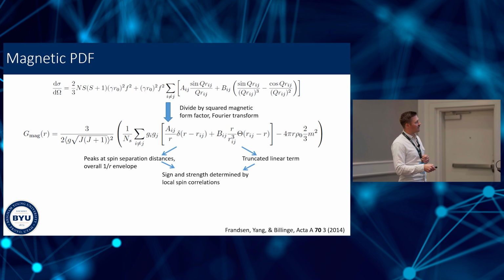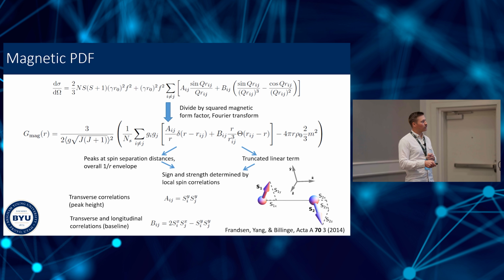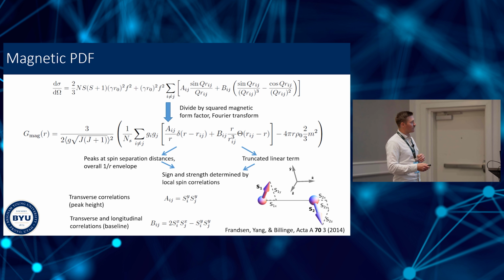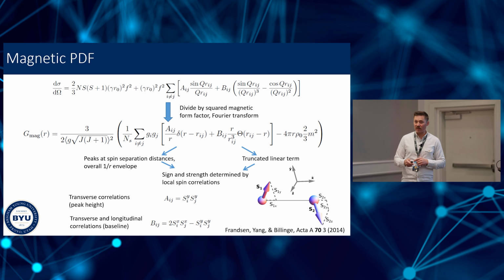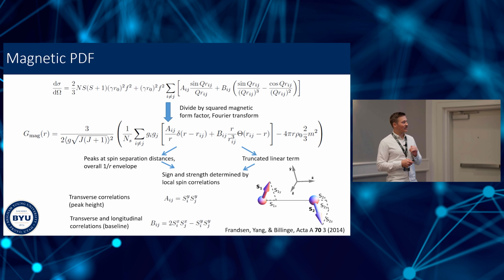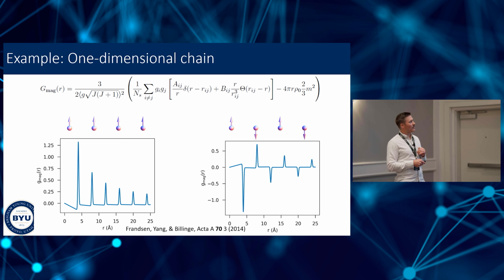The A coefficients give information about the transverse correlations between a pair of spins, transverse to the direction joining those two spins, and B contains information about both the longitudinal and transverse correlations. These details are not so important because when you actually use this expression to calculate the magnetic PDF for some given magnetic structure, it's very intuitive. This is the nice thing about magnetic PDF. So let's say we have a one-dimensional chain of spins that are aligned with each other.